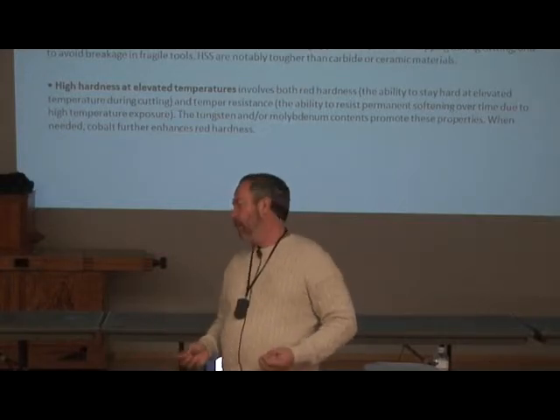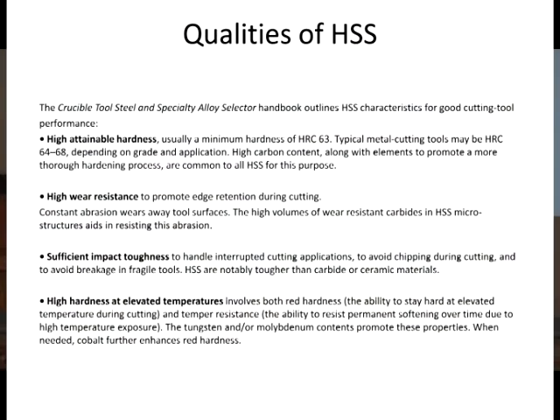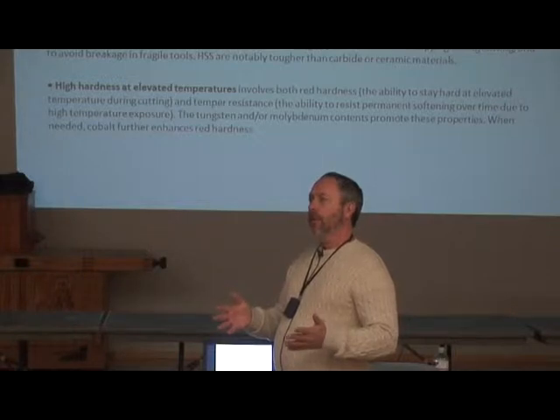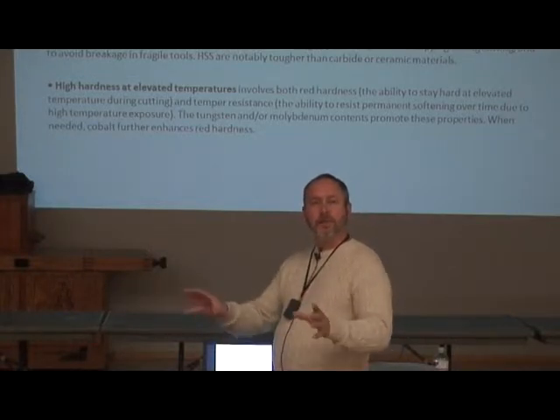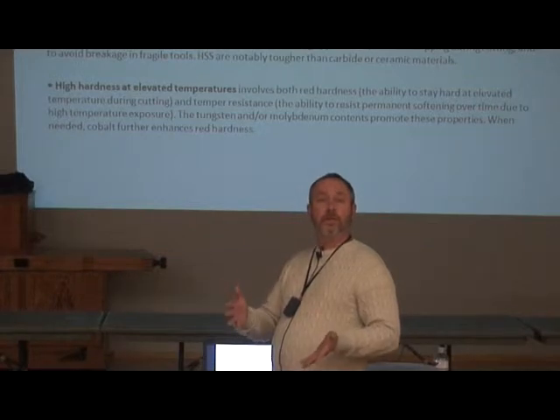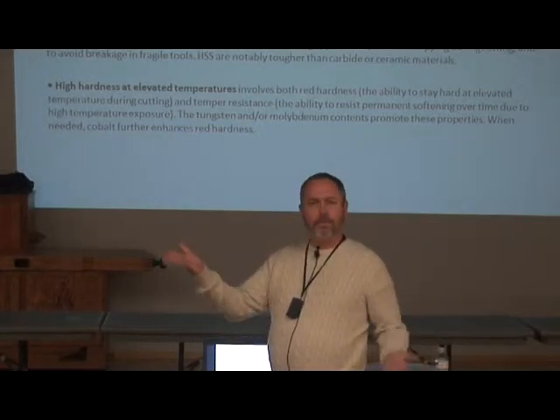So the next development they came into were your high-speed steels. There again, here are some of the basic characteristics. High attainable hardness, very hard, Rockwell C. A very hard knife is in your Rockwell C 61, 62, 63 type for a reference. If you have a scraper, something like that that's flexible, those are Rockwell C 52, 53. Relative comparison.